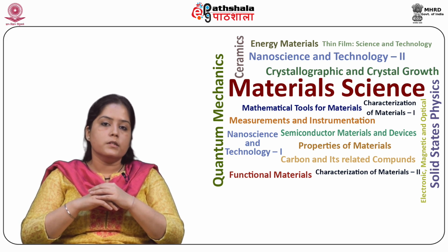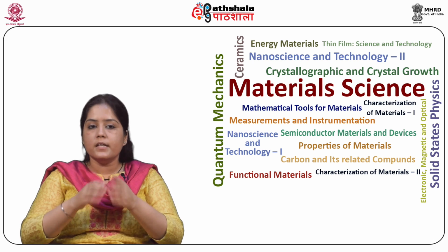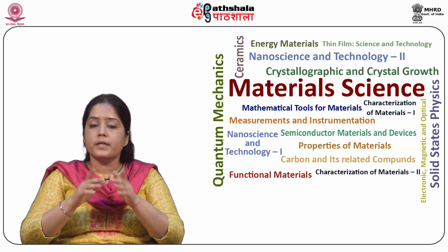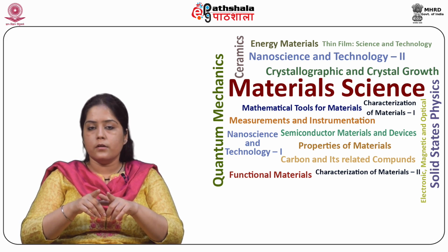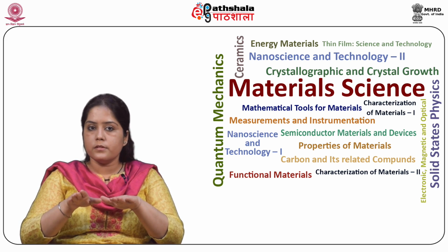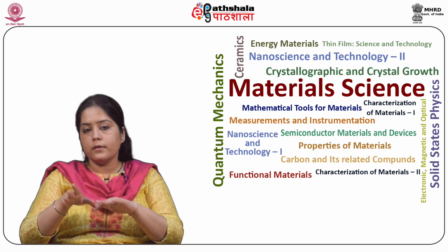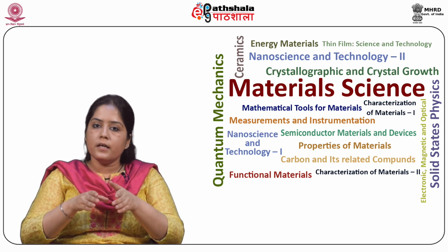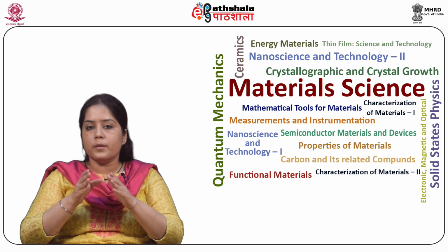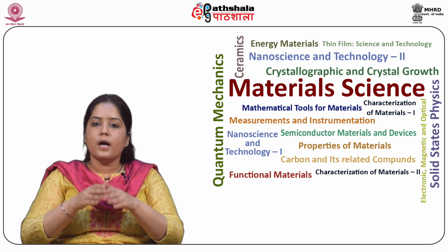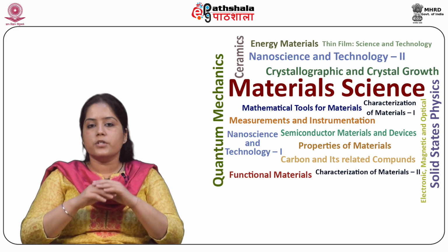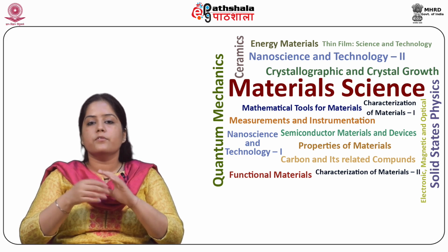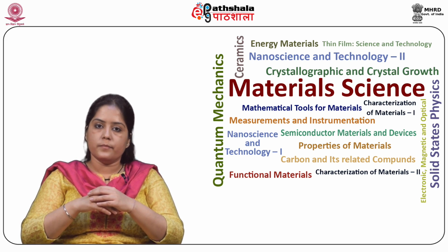Although the transfer of vanadium ions through the membrane was found to be highly dependent on the concentration difference between the positive and the negative electrolytes, cation and anion exchange membranes tend to have net volumetric transfer towards the positive and the negative compartments respectively.